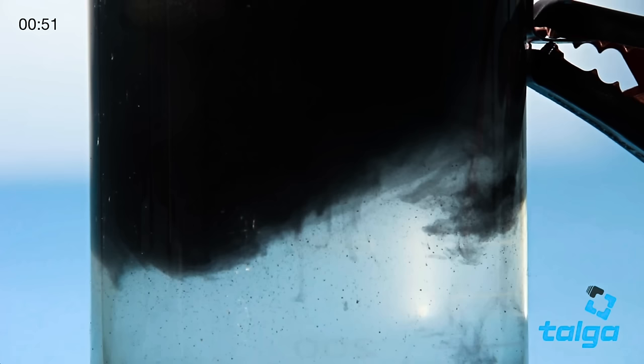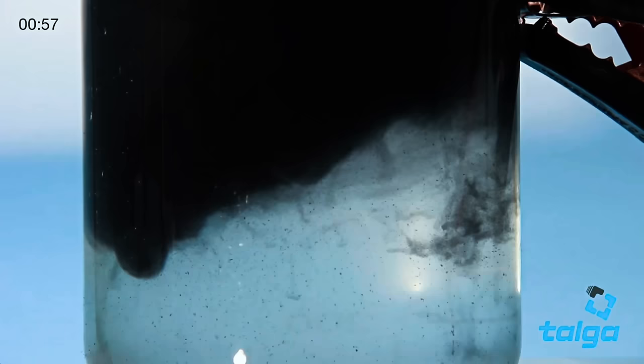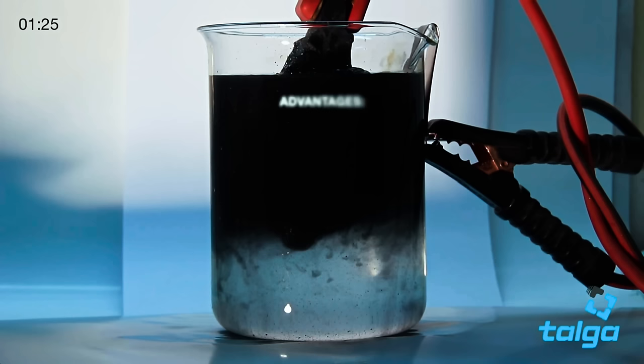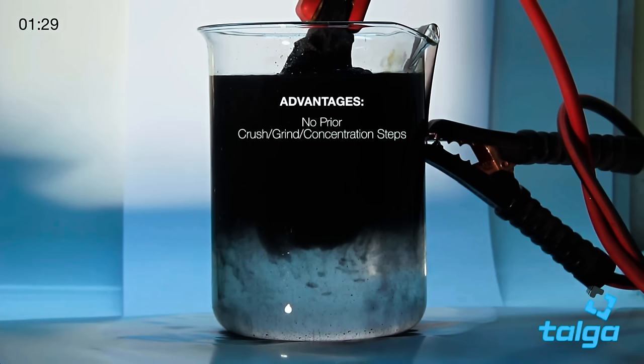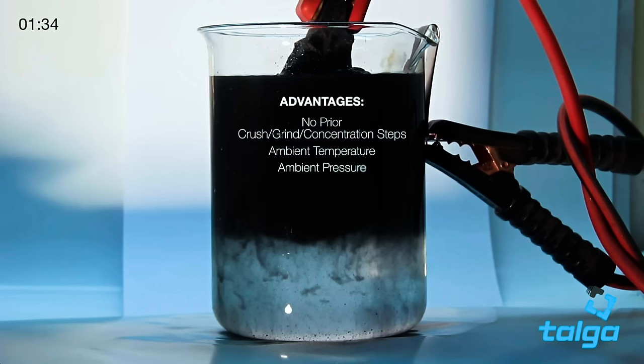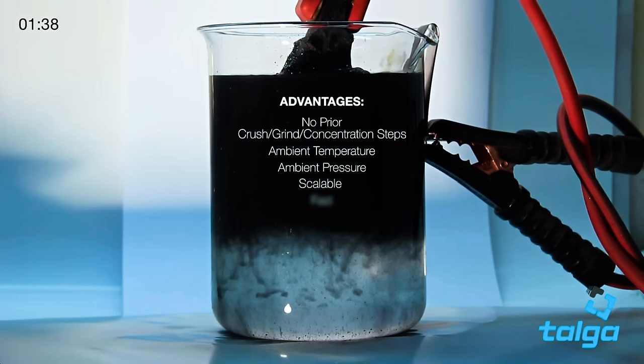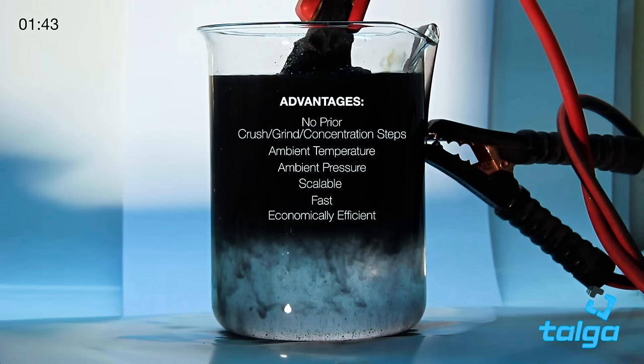You might assume electrochemical exfoliation requires toxic or exotic chemicals. However, the research I've found indicates the solution can be made with chemicals as simple as ammonium sulfate, which is a cheap bulk material that's often used as a fertilizer. This doesn't rule out toxic side reactions, but we can't know for sure without knowing more about Talga's process or formula. In general, the process isn't without its challenges. For example, the graphite can disintegrate before it's fully exfoliated into graphene.